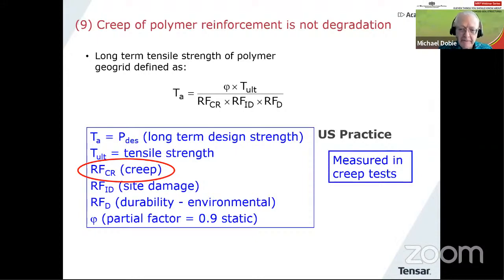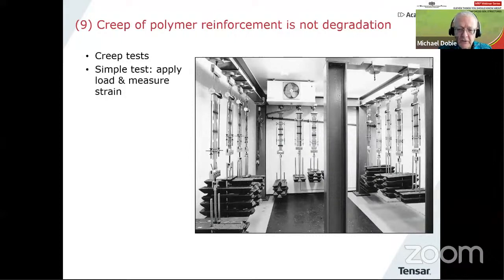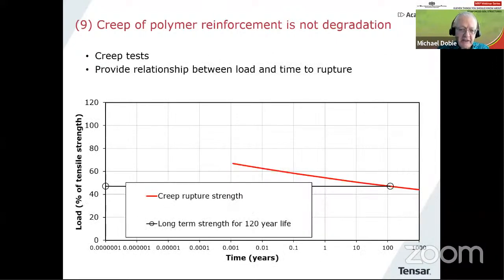I want to talk briefly about creep. A creep test looks like this, whereby we hang up a sample, we put a weight on the bottom, and we simply measure strain against time, and we leave it there for a long time. This gives us a very good idea about long-term performance of these materials. And then the data is plotted in this way, where we have the load applied versus the time, in this case, to rupture. And the relationship is that red line you can see there. The time axis is logarithmic and it's in years. So I've put a dot there at around about 120 years, which is a typical design lifetime. And then that gives us the load we should apply to make sure that the rupture only occurs at that point in time.